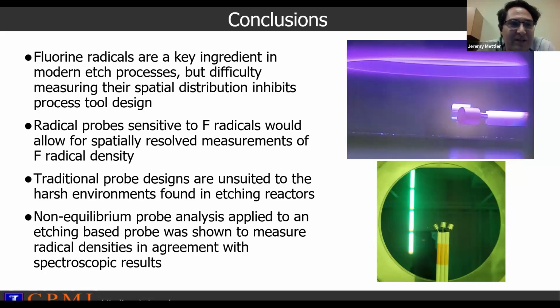But just to wrap things up, fluorine radicals are a key ingredient in the modern etch process, but attempts to measure them using traditional radical probe designs proved that, at least with the materials we tested, the traditional design was unsuited to the technique. However, by combining a non-equilibrium analysis technique with an etching-based probe, we were able to get some pretty good results for radical densities that agreed with the accepted spectroscopic measurements.